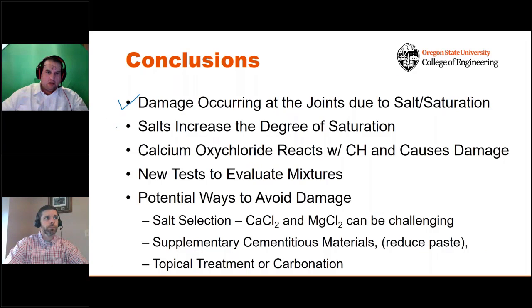salts and saturation. Salts increase the degree of saturation. Oxychloride reacts. It comes from a combination of the calcium chloride and the calcium hydroxide. We have new techniques to look at these mixtures. We have several ways to avoid this damage.